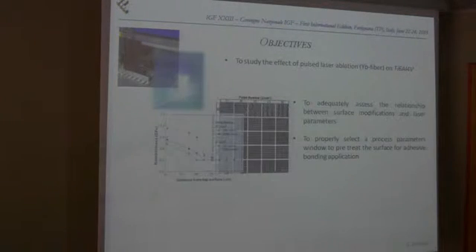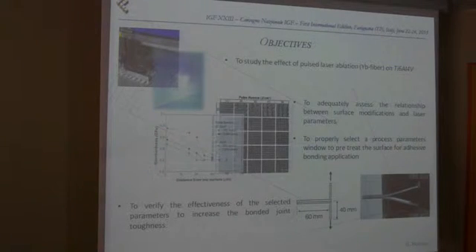So the objectives of this work will be to study the effect of a pulsed laser ablation, which is a ytterbium-doped fiber laser, on a titanium alloy, which is one of the most commonly used for aerospace and biomedical applications. And doing this, we want to properly assess the relationship between the processing parameters that we are using on the laser and the surface modifications that we are inducing over the mating surface. And doing that, we can select proper processing parameters in order to pretreat the substrate, to bond it together, and to verify if we can increase the strength of the bonding of the joint itself.